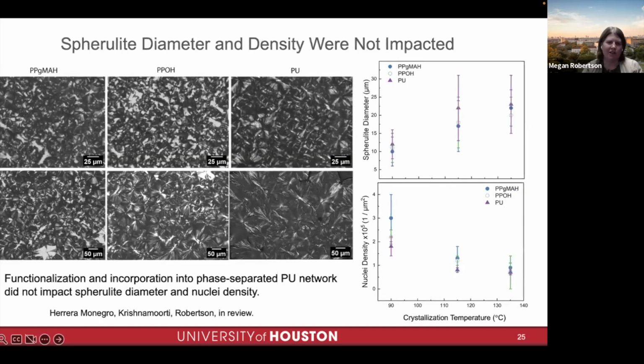If we zoom out and look at the spherulites, here are some nice images under cross-polarized microscopy. Of course, we could look at the crystallite diameter or the nuclei density as a function of the temperature we crystallize the material at. But what's noteworthy here is that all of our materials have very similar size of spherulites at a particular temperature, which again tells us that incorporating this polymer into this polyurethane structure is not changing how it crystallizes.